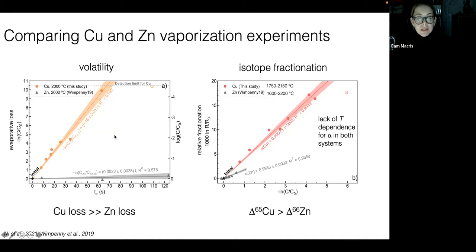So here we're comparing directly the copper and zinc results from these experiments. On the left, we're comparing the evaporative loss of copper, in orange, versus zinc, which is in gray here. And what we see is that copper is considerably more volatile. This line is way more steep than zinc at the same temperature. And then on the right, we're comparing the isotope fractionation between copper and zinc in these experiments. We see similarly that copper, which is now shown in red over here, is more fractionated at similar temperatures than zinc, again shown in gray. Both systems showed a lack of temperature dependence at these high temperatures for the fractionation factors. It's worthy of pointing out.